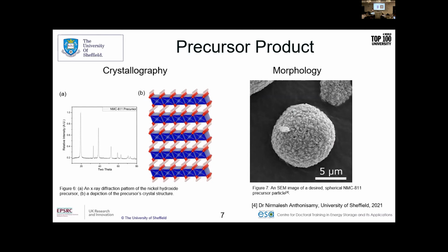And this is evident in the XRD patterns, which show nice sharp peaks for this nickel precursor fingerprint. These nice sharp peaks show more layered structure because of the crystallinity of the system.